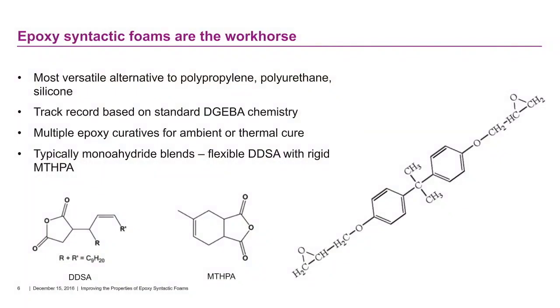So of the different syntactic foam formulations that are available today, the workhorse and the one with a fairly long established track record have been those based on epoxy resin chemistry. Very standard DGEBA resin is utilized, and that type of resin can be cured under ambient or thermal curing conditions. Elevated temperature curing is really the way to go in order to drive the properties that we have been mentioning so far. And the monoanhydrides listed here have been the traditional go-to curatives. The more flexible DDSA on the left and the more rigid MTHPA on the right are used in different combinations with this standard epoxy resin and can produce very suitable epoxy syntactic foams and work well in service.